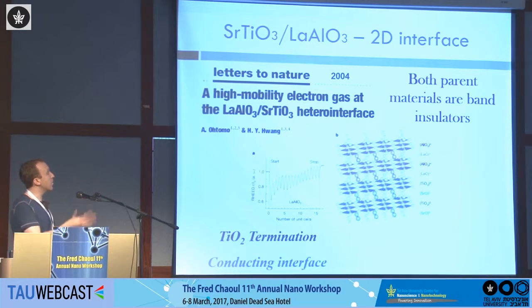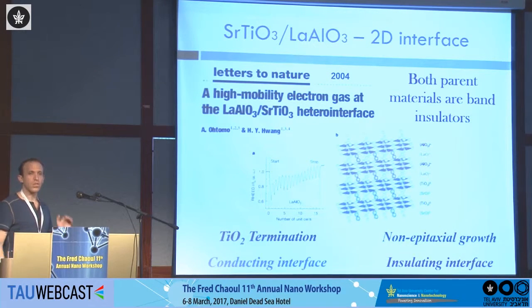What is that? It's two band insulators, lanthanum aluminum oxide and strontium titanium oxide. But when you grow the lanthanum aluminum oxide on top of a TiO2 terminated STO, you get a conducting interface, which is actually two-dimensional, okay? I want to stress that if you don't grow it epitaxially, it means that the lanthanum aluminum oxide is not a single crystal now. You get an insulating interface, and this can help us in our fabrication.